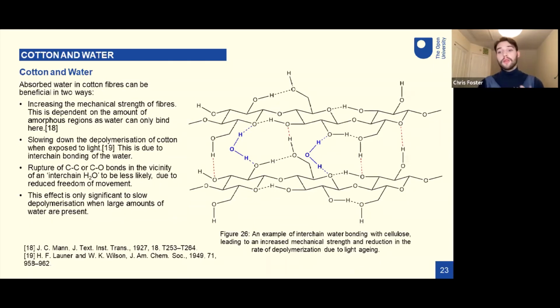Another impact this interchain water bonding can have is it can actually slow down the depolymerization of cellulose when exposed to light. Now, this is a fancy way of saying the degradation that occurs to the polymer, the breaking down of the polymer as a cause of light. And this happens because when the water molecules are bound in between those chains, there's a reduced freedom of movement in the chains. And when light is causing bonds to break, it's much less likely to occur because there's this reduced freedom of movement. I should point out this effect is only significant when large amounts of water are present, particularly if the fibre is immersed in water.